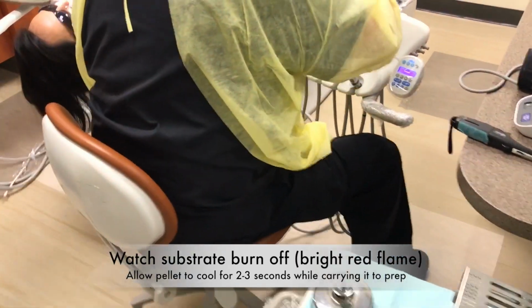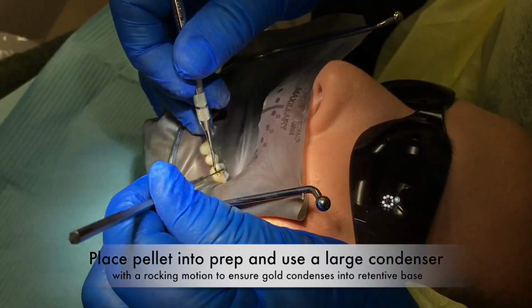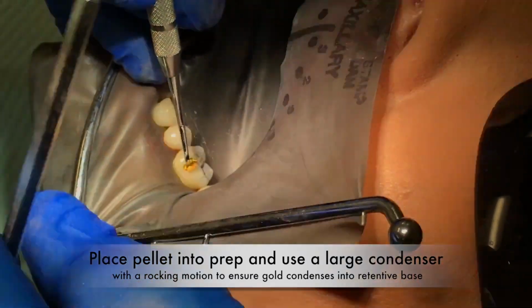The tooth to be filled must be isolated from the saliva using a rubber dam and thoroughly dried to avoid contamination during condensation. Condensation or plugging of the gold may be carried out by hand, with an automatic mallet, or by the application of a mechanical vibrator. The use of an automatic mallet involves the application of a relatively large force at infrequent intervals, whereas a pneumatic or electrically driven condenser delivers much lighter but more frequent blows.